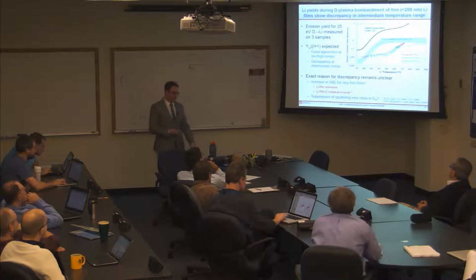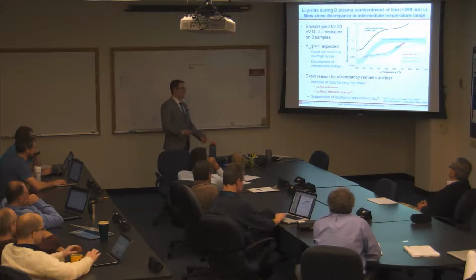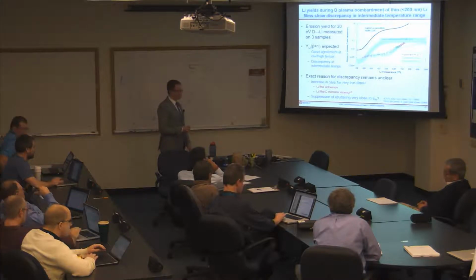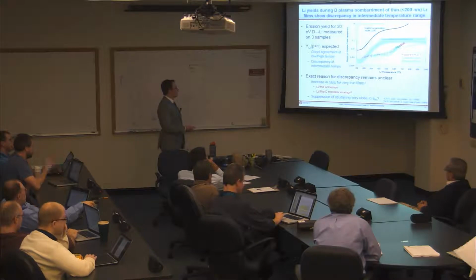Okay, so what about the very thin film case? For the thin film case, you would expect that basically the deuterium would saturate the lithium almost instantaneously. It actually happens within about a millisecond if you use the diffusion model. So you'd expect that you have the fully saturated case, the beta equals 1, throughout the entire temperature ramp up of the discharge.